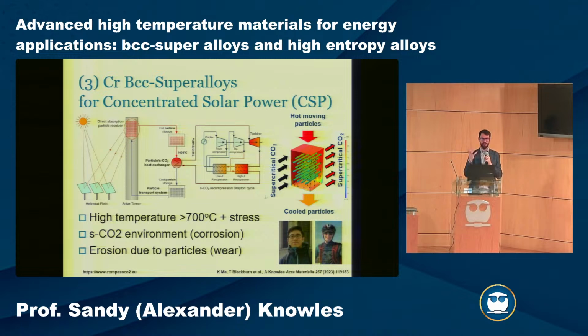At the central tower, you can get to really, really high temperatures, so you can melt steel very easily. You can go to 2,000 degrees if you wanted to. Basically, it just depends on how much coolant you put through, but these are very, very high heat depositions. The technology being pursued by our consortium, but also by Heliogen, a multi-billion-dollar unicorn startup in the US, is to use ceramic particles as the heat transfer medium. They have good stability and high energy density, and you can take these hot particles and store them. So when the sun isn't shining, the particles stay hot, and you have a way of storing that energy over time.